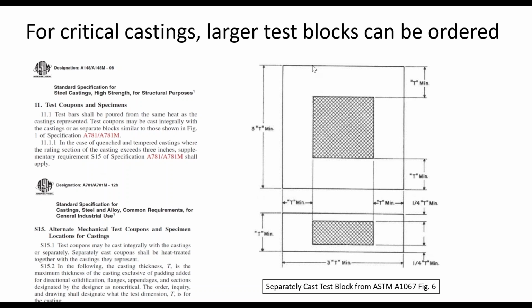S15 says you have to cast a separate test block that's big enough to emulate. So T is the thickness. So this says when T is over 3 inches, then I have to make a test block. And that test block, if it was 3 inches, would be 9 inches by 9 inches by 3 inches thick. And I would take the test at T over 4, or 1/4 of the way to the center. T over 2, I'm in the center.